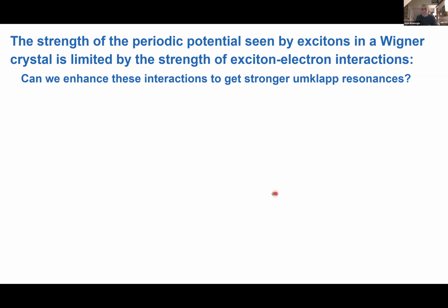Absolutely, excellent question. This is precisely the reason why only 2 of the 6 umklapp resonances that I've shown are allowed to hybridize with the k equals 0 fundamental exciton peaks and acquire oscillator strength. Basically, it is the perpendicular angular momentum, mod 6 in this case because of C6 symmetry. The states that can hybridize are those with L sub z equals +1 and -1, and the others remain dark because their angular momentum doesn't allow them to hybridize.